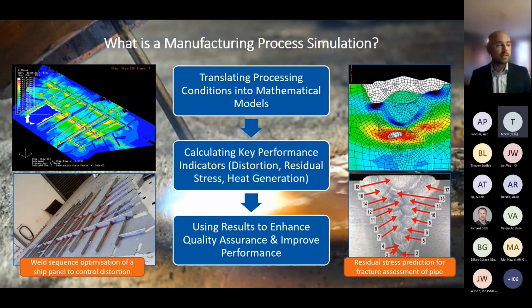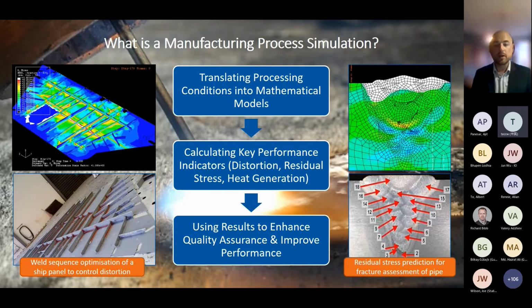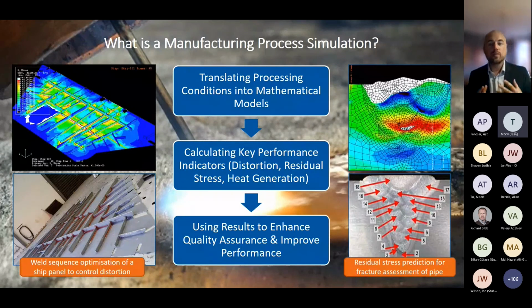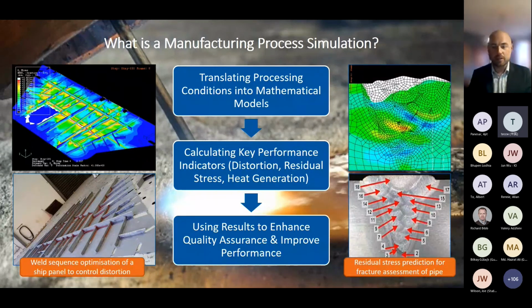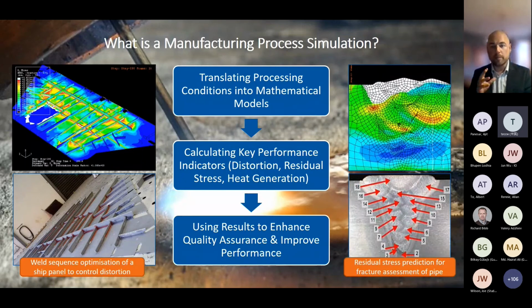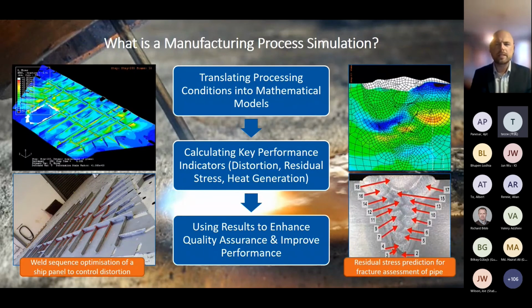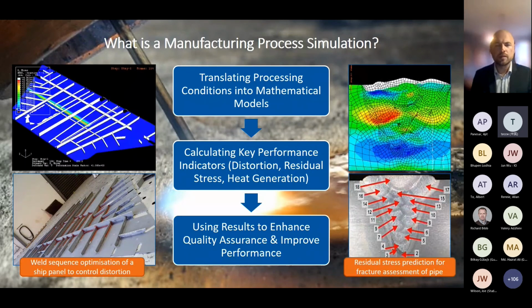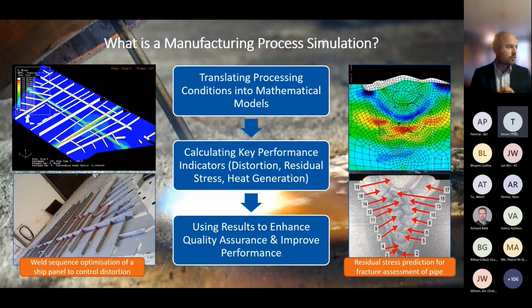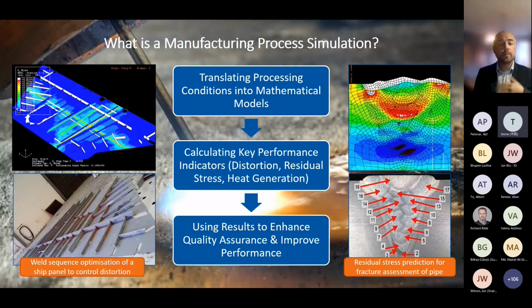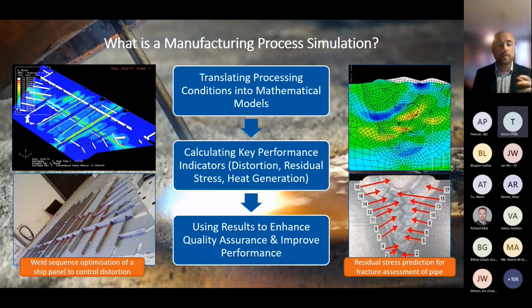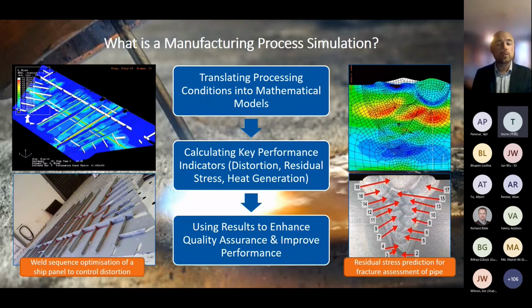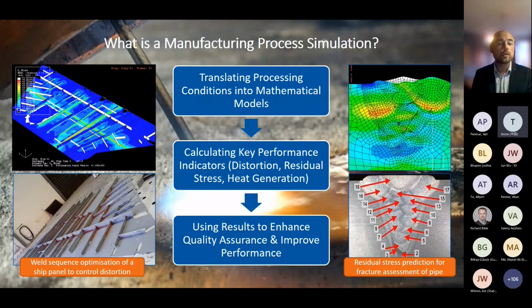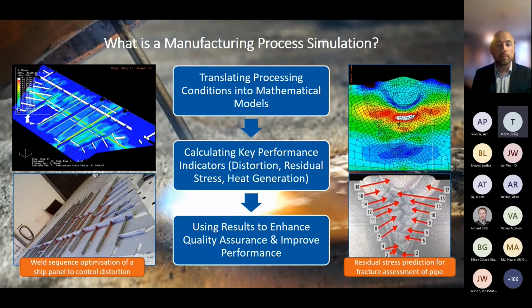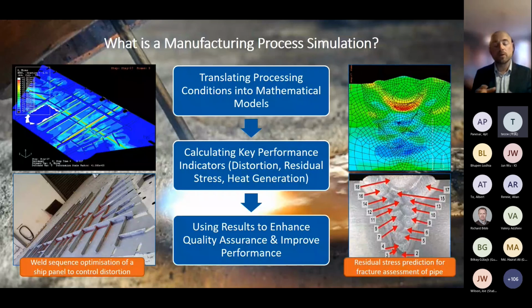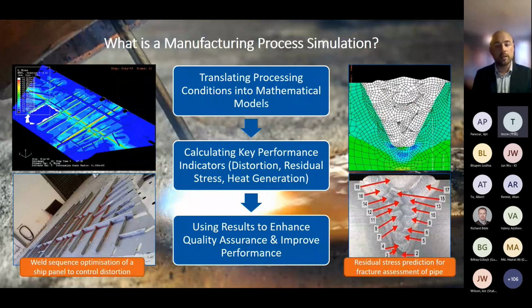And there's no one-size-fits-all model. It could be a model for detailed residual stresses in a nuclear application like we see on the right. There we're looking at bead by bead and really detailed constitutive behaviors. But if we're looking at weld sequence control for distortion, it might be a much higher level model that's capturing only the physics that are relevant. And the same is true for additive manufacturing. We're using an existing thermal mechanical modeling framework, but trying to put in the right ingredients to calculate what we need.